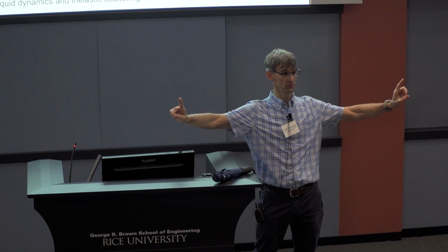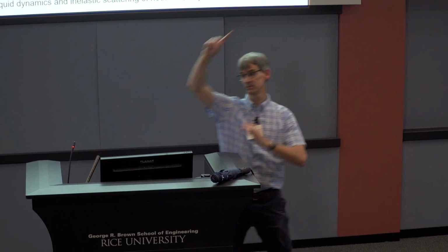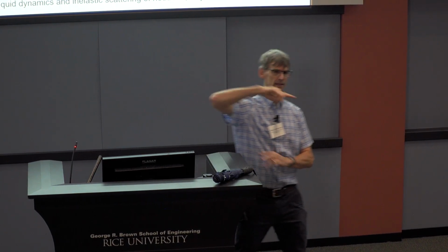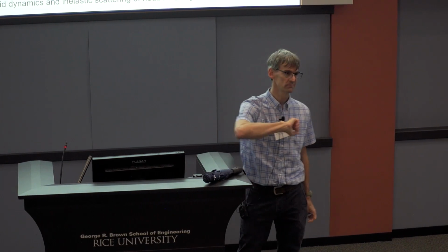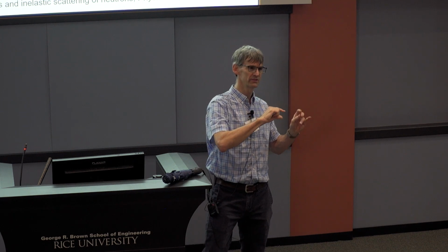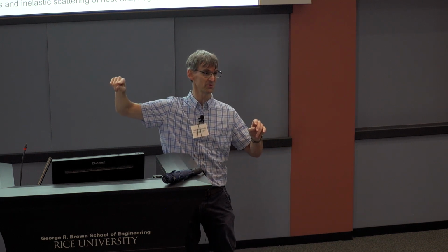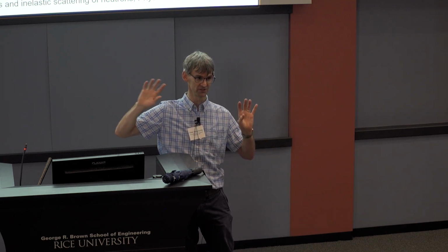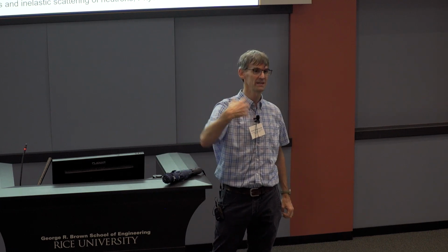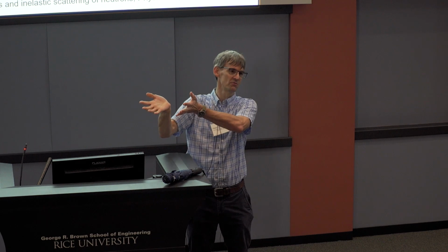With 2, it goes down, then it comes up, and then it goes down again. So basically, you are still measuring sort of a microscopic part of the response. Yeah, and then there's a conversation whether those 2 minima have the same curvature and give you the same diffusion constant. They should. But if you do the same thing in liquid helium, you get 2 minima, and one of them they call a Roton minimum.